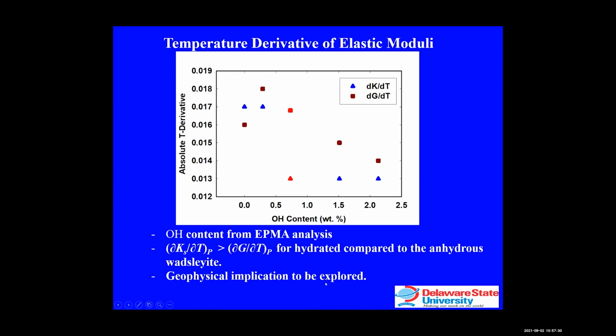So we are still going through this, we just obtained the water content, and we'll spend some time now, first of all, clarifying the issue about the higher pressure derivative of the bulk modulus compared to the data from the Brillouin scattering, and also see whether by changing the cell assembly, anything will happen, whether there will be some changes in the temperature derivative of the elastic properties too, because these are the first measurements and we don't know what will happen, whether there's any effect of stress on that. So we have to clarify this and then go on to do the geophysical implications.